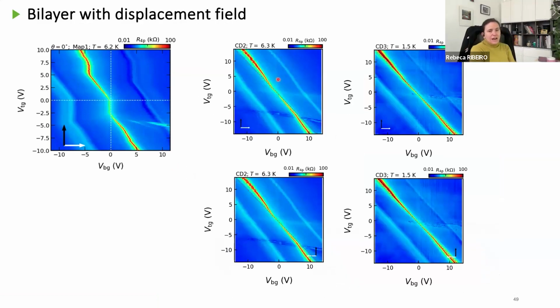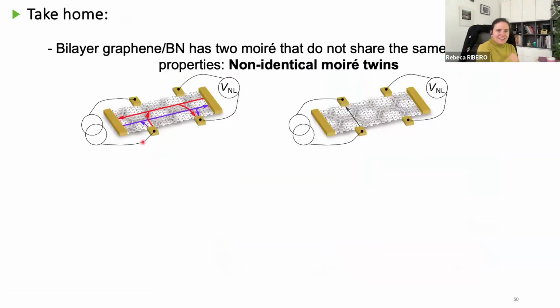In fact, these are just different cool downs of the same sample. You can see cool down 1, we saw a beautiful ferroelectric state or hysteretic state. Then for cool down 2, it's almost gone, and for cool down 3, it's practically gone. So with this, since I'm running out of time, I would like to give you the take-home message of this